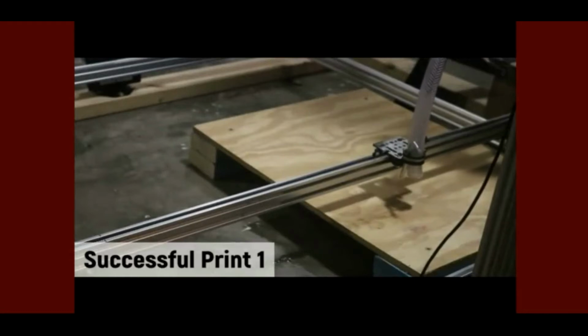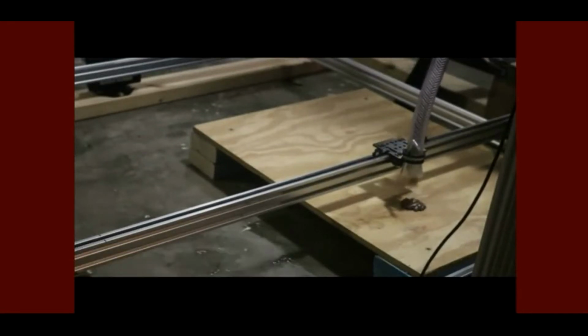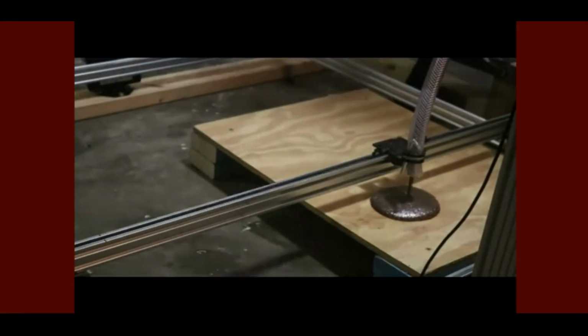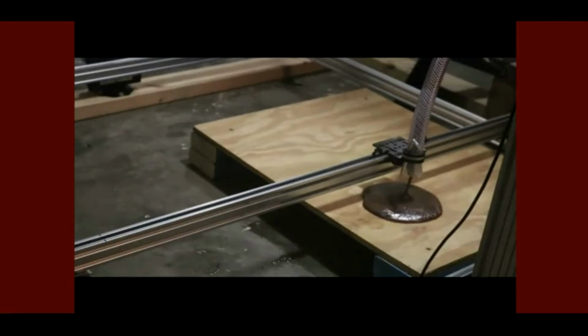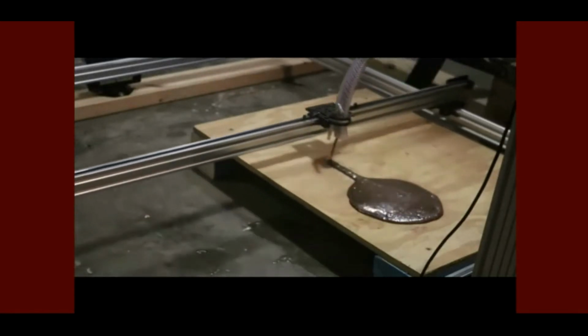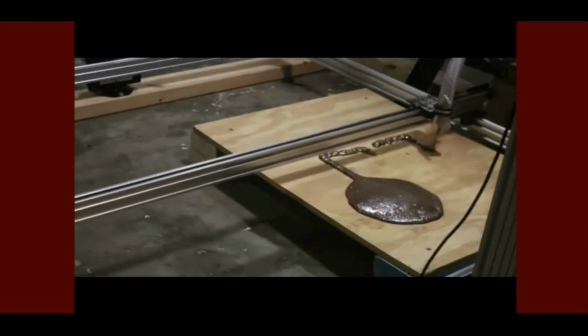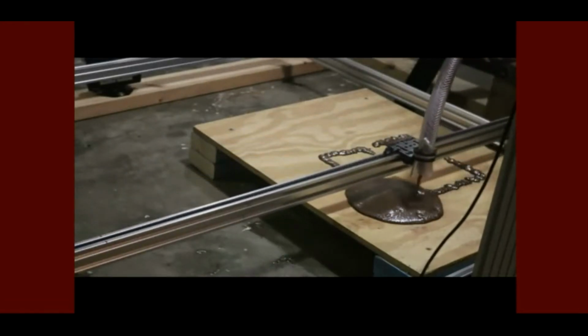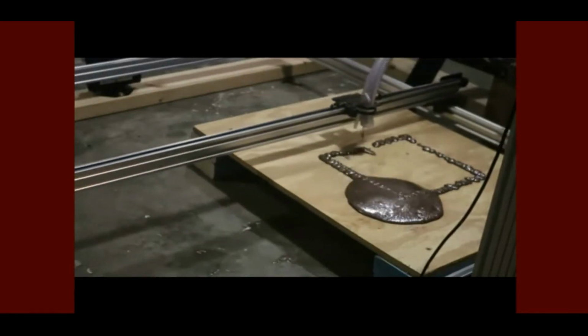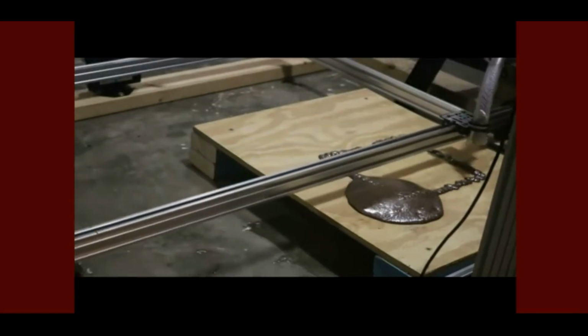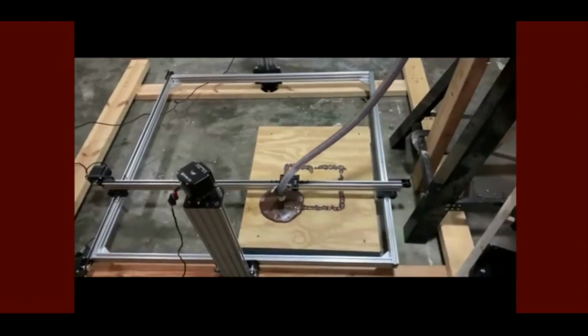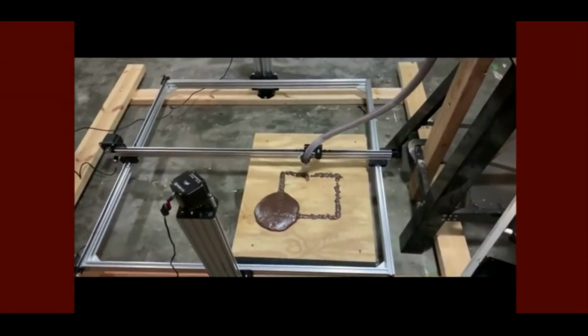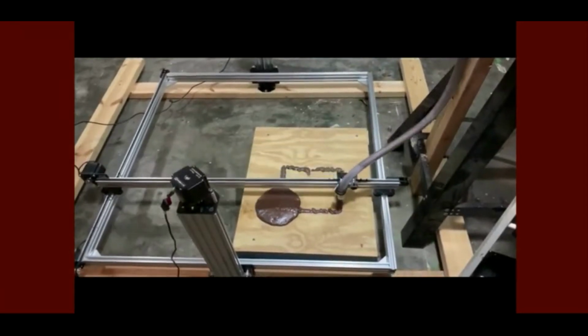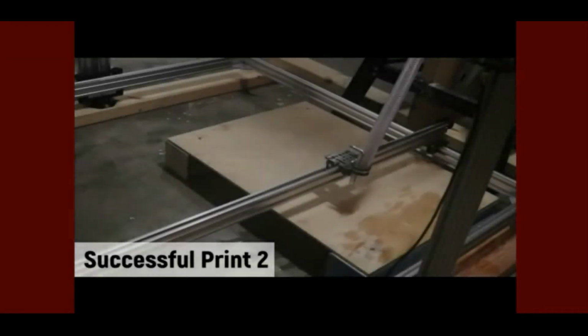So here's the first successful print. As you can see here, it actually just comes out in one spot for a little while and forms sort of a puddle. That's actually because the programming was starting a little too late. So you'll see it does start moving eventually, and it does manage to trace that program 20 by 20 centimeter square, which demonstrates that I was able to program the printing of sulfur concrete in this trial, even though it was kind of clumped and it wasn't able to layer up because I was limited on how much I could pour through at a time, simply based on how it would start to solidify in the tube.